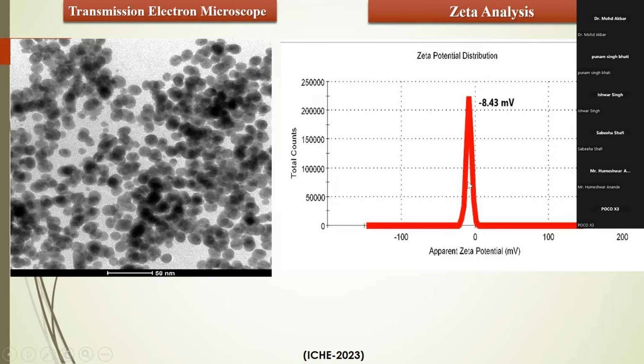And to confirm the stability of the synthesized nanoparticle, the zeta potential was used to characterize this, and it was concluded that all the nanoparticles present in the prepared solution possess a minus 8.43 mV zeta potential value, which confirms that all the nanoparticles present in the solution possess negative charge on their surface that prevents their agglomeration and hence increases their stability.